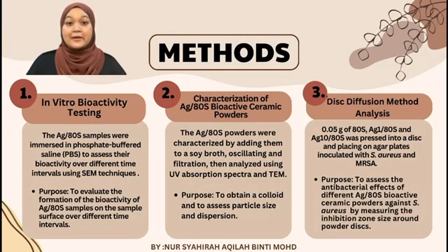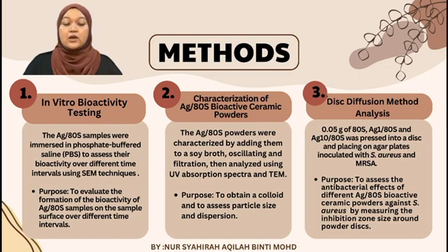In this slide, I will explain three major methods in this research. The first method is in vitro bioactivity testing. The samples, which are 80% silica-based calcium phosphate, and 1% and 10% silver with silica-based calcium phosphate, were immersed in phosphate buffer saline (PBS) to assess their bioactivity over different time intervals using scanning electron microscopy. The purpose is to evaluate the formation of bioactive layers on the sample surface over different time intervals, which are 10, 24, 48, 72, and 168 hours.